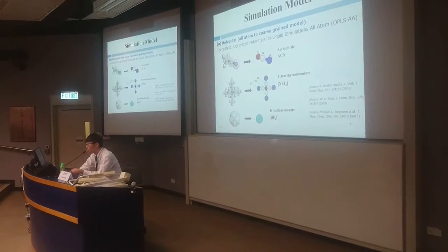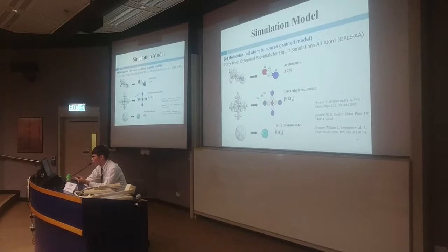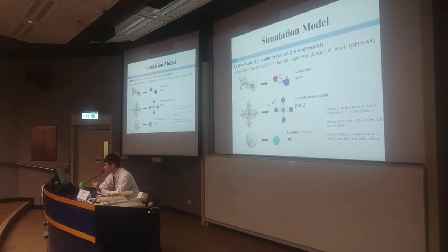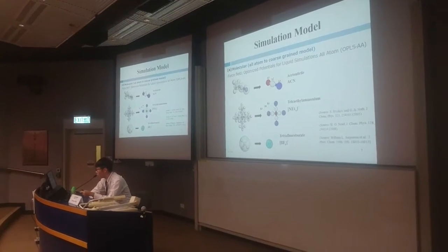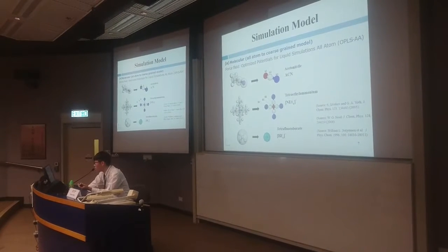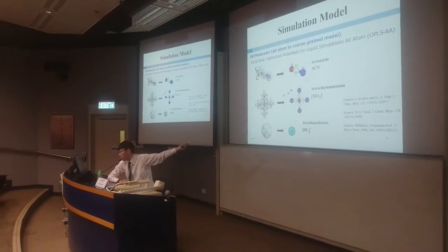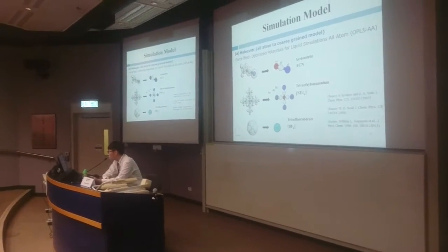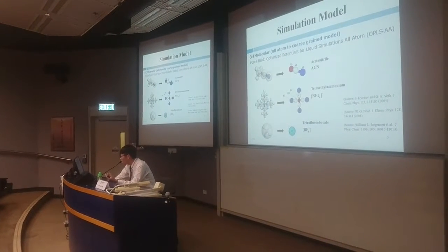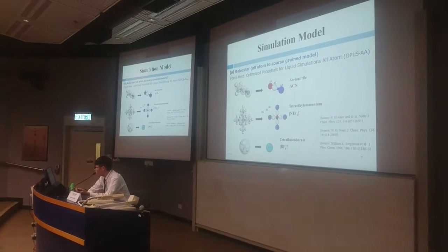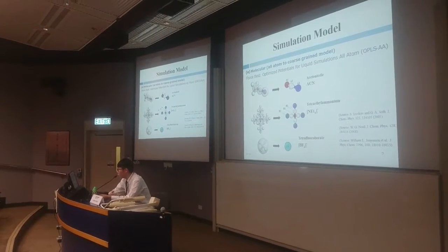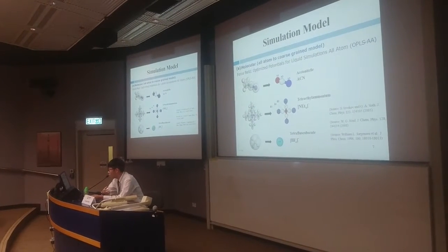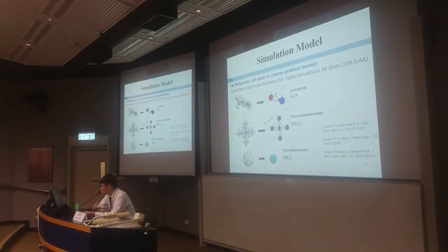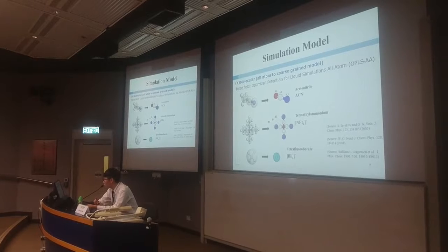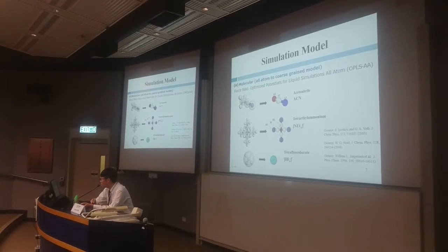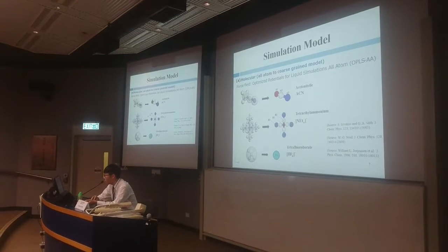In order to reduce the numerical calculation time for the large number of systems, the electrolyte has been coarse-grained. So in this slide, we show the all-atom molecular structure in the OPLS model and the coarse-grained model. So we use the optimized potential for liquid simulations, OPLS-AA, to describe the interactions between the atoms, which was proven as a good molecular description of organic liquids in the previous work. So we use the OPLS-AA as a force field to generate the reference data and then